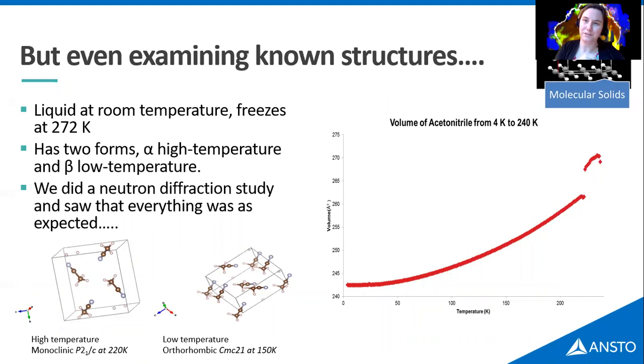But even when we know the structures, some surprising things can happen. And I thought the story here starts with acetonitrile. So acetonitrile, pretty well studied. It's a solvent used in many people's labs. We know it has two phases, an alpha form and a low temperature beta form. We did some neutron diffraction. We just wanted to see the thermal expansion. As you can see, this just shows how awesome Wombat, the instrument that I run, is, where we can take data within 1 to 2 minutes, even from hydrogenous materials. And so we've got a really nice thermal expansion there. So that was a really nice example.